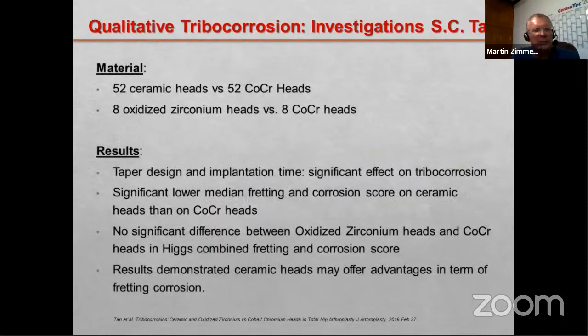So they used for their analysis 52 ceramic heads versus 52 cobalt chrome heads, which is about the same as the study by Steve Kurtz. And also with the group of oxidized zirconium, there were 8 oxidized zirconium versus 8 cobalt chrome. I should say from a statistical relevance standpoint, this is a bit too low to make very secure conclusions from the study.